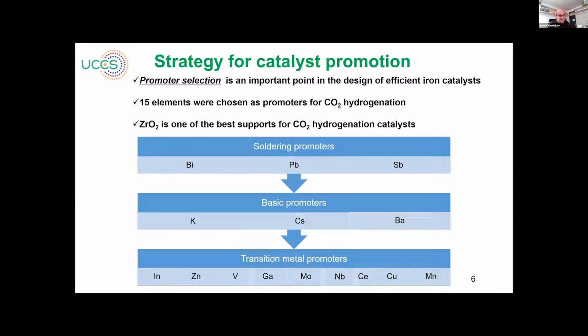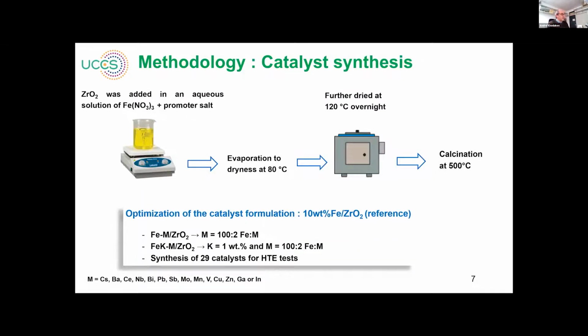The strong point of our work is that we prepared the catalysts with the same molar concentration of the promoter. We use 10% of iron, and all the time we prepared the catalyst with promoter where the ratio of iron to promoter was 50, in most cases. Here is the methodology for how we prepare the catalyst. We prepared by impregnation using zirconia and added a solution of iron nitrate and promoter. Then evaporation to dryness, and the catalyst was dried and calcined at 500 degrees. Typically the ratio for metal to promoter was 50, so 100 to 2.